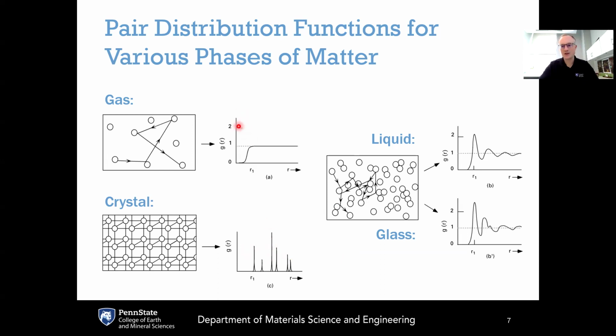Now, if we take the opposite extreme, the most disordered phase of matter would be a gas. And if you have a monatomic gas, this would be like a noble gas like argon or neon. Here, the pair distribution function is 0 at short distances because of Pauli's exclusion principle. This means that you cannot have the atoms of the gas existing on top of each other. And so it's 0 at short distances. But then it just goes straight to 1 because you would have complete randomization after that.